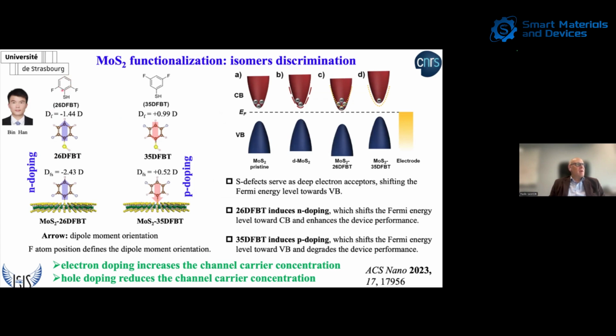It is a molecule that comprises a benzene ring, a thiol unit to anchor the molecule on the basal plane of the molybdenum disulfide, and two fluorine atoms that are either pointing down or pointing up. This is interesting because you can orient the molecular dipole either out of the surface or towards the basal plane of the surface. What does this mean? Orienting the dipole in a controlled manner means that you are able to have a strong n-doping effect when you use the 2,6 derivative, or a strong p-doping effect with the 3,5 derivative.